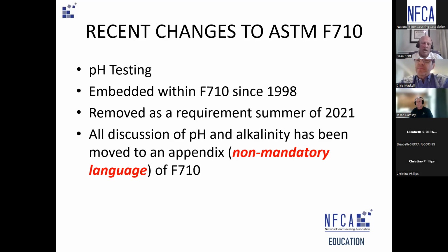I think the whole mechanics of pH, what they're getting at, goes back to your moisture testing. If the moisture content of your concrete is low enough and the adhesive is being applied correctly, then there should be no condition where a pH issue manifests. And like I said, there is literature that shows there's enough water in some of these water-based adhesives that it itself can induce alkali hydrolysis if it's not allowed enough open time and it's non-porous. You put it down and you close it up too quick with your resilient flooring. So it's been removed from F710. There is a separate standard, but it's been pushed down to the manufacturers, whether they require it or not. So that's where that stands right now.